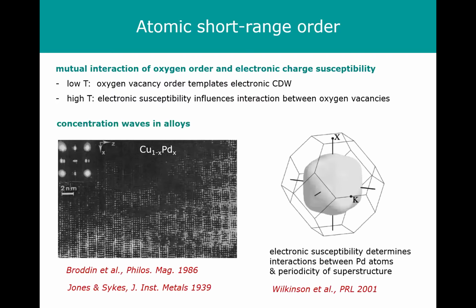But then, there's a converse effect at high temperatures. At high temperatures, the oxygen are still mobile and they interact somehow, right? And then as you lower the temperatures, these oxygen vacancies freeze in. Okay, and this interaction is also determined by the susceptibility of the electron gas. And this kind of effect has been already known since the 1930s, really, where in these metallic alloys, people saw concentration waves of the alloy composition that matches characteristic features in the electronic susceptibility.